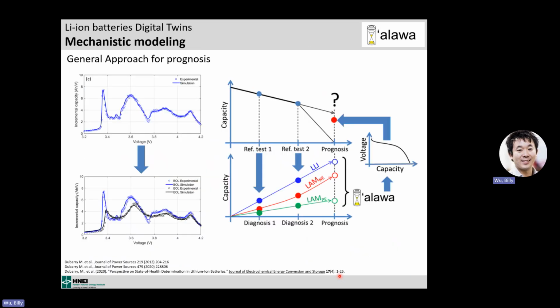So to do prognosis, what we recommend is to do several diagnoses, at least 3, and then try to extrapolate on the degradation model level so that you can predict the needs. And we showed many times that you can predict some needs that way. So it's a much better diagnosis than just looking at capacity and power.